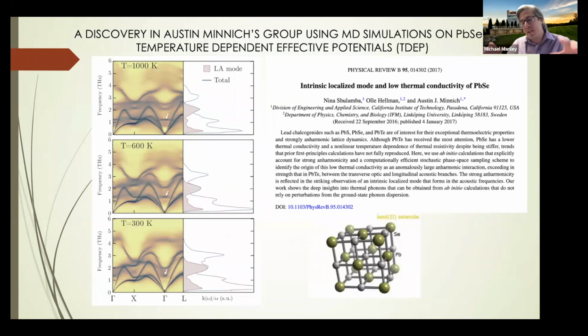So none of this classic approach where you just freeze in a distortion and get force constants. That's very expensive computationally. But Olle came up with a way to do this where you let it go, calculate it instantaneously, and then accumulate information that allows you to extract force constants, first, second, third order, and higher order, and then do a simulation that includes everything. And then you just calculate the spectral function.